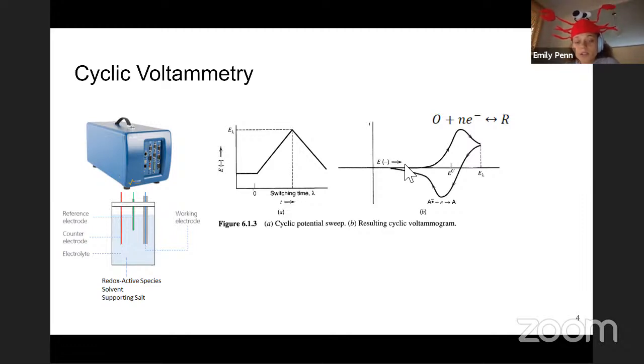So here's what a CV looks like for some system where you have some species O, and you're forming some reduced species. Your current potential plot would look something like this, where you see it peaks, and then as you reverse the potential, you get a peak in the opposite direction. This might look kind of weird. So this plot is from Bard and Faulkner, and they use a different convention for the current.